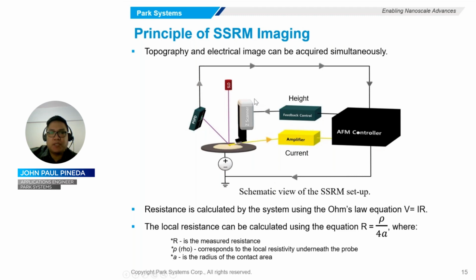Right, so let's proceed with the principle of SSRM imaging. As I mentioned a while ago, SSRM is also an AFM-based technique. Therefore, a topography image can be acquired simultaneously with the electrical properties of the sample. In acquiring the topography or height image, the vertical deflection of the cantilever is measured. As you can see here, a laser beam bounces off the back of the cantilever onto a position-sensitive photodetector, also known as PSPD. As the cantilever bends, the position of the laser beam on the detector shifts. These changes are then measured and processed by the AFM controller to obtain a height image.